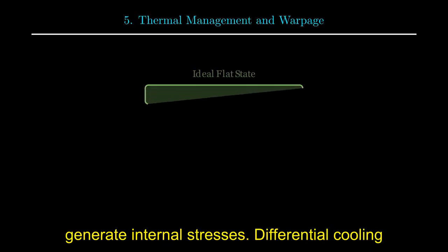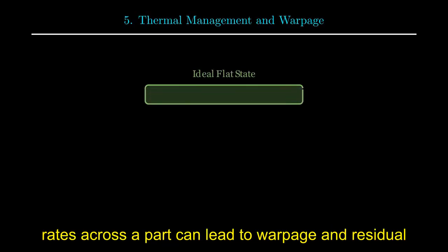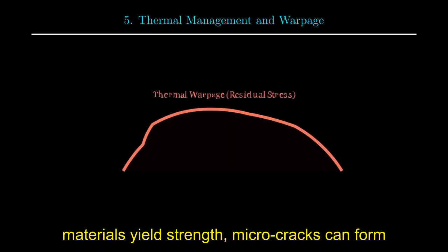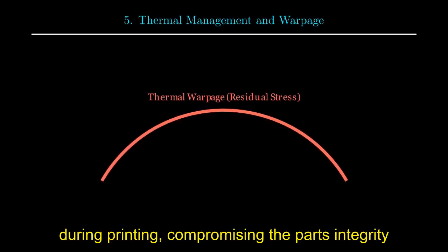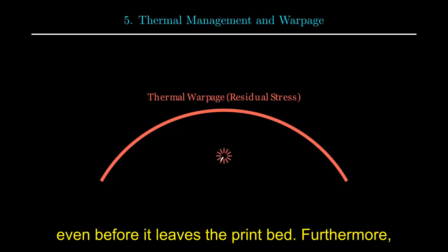Thermal management during polymer printing presents another critical challenge. The controlled heating and cooling of successive layers generate internal stresses. Differential cooling rates across a part can lead to warpage and residual stress accumulation. If these stresses exceed the material's yield strength, micro cracks can form during printing, compromising the part's integrity even before it leaves the print bed.